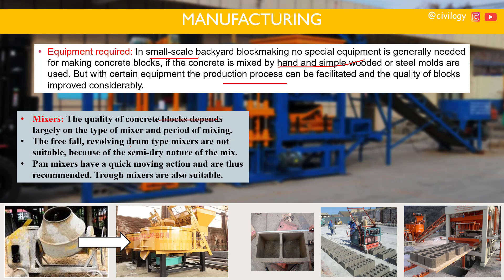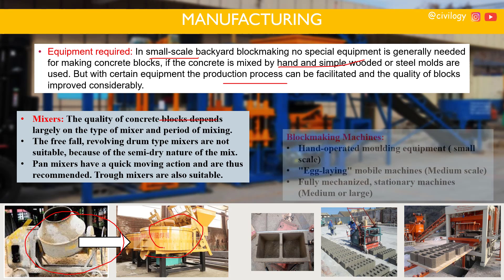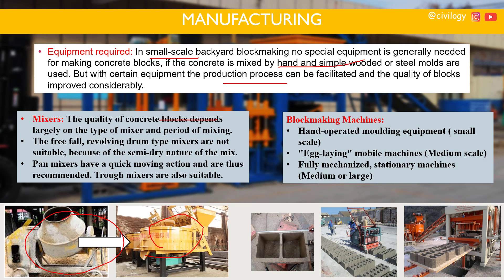The quality of concrete blocks depends largely on the type of mixer and the period of mixing. Free-fall and revolving drum type mixers are not suitable because of the semi-dry nature of the mix. Pan mixers, which have a quick moving action, are recommended. Trough mixers are also suitable. So you can use trough mixers or pan mixers for this manufacturing purpose.